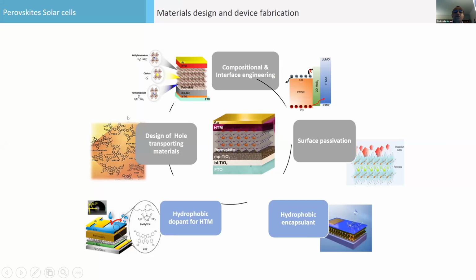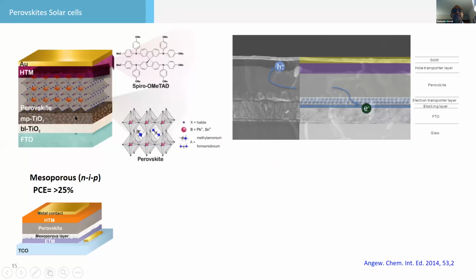We are also interested in designing a hole transport material, a P-type material. P-type material, as I said, is very good as a hole transport material in our organic solar cells, here in our perovskite solar cell. This is the cartoon of the device, and you can see the layers, there are three to four layers. This is the perovskite layer, which is sandwiched by an N-type layer. The N-type layer is generally titanium dioxide. We also use tin oxide. You can also take zinc oxide or PCBM, and then you have a hole transport material. Perovskite absorbs the light and generates an electron and hole pair, which travel to their respective electrodes to get collected. Most of the time the HTM is a spiro, but Samana will talk today about new types of spiro, new types of HTM, which can be more effective. This is a cross-section diagram, a cartoon of the device.